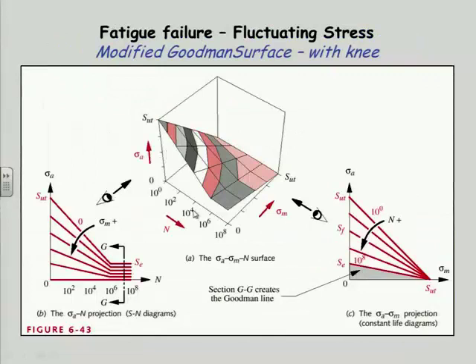So this is an attempt to plot the three axes that we've so far discussed. This axis is number of cycles, and I've gone from 10 to the 0 to 10 to the 8 here. And this is the alternating stress axis. So this picture, if I look in, there's my eyeball looking in that direction, and draw that side view, each of these lines is an S-N diagram, strength versus number of cycles, showing an endurance limit, so it's presumably steel. And what I'm doing is I'm cutting through this at different levels along the mean stress axis. So the mean stress axis is going back, taking my endurance strength down to 0 at SUT.